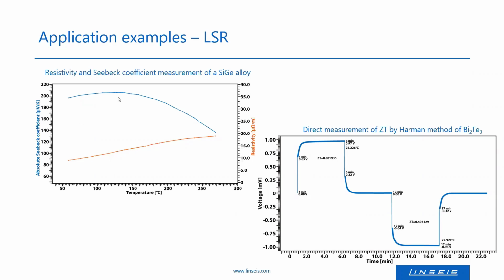Here on the top, one can see a silicon germanium alloy, which is a typically used material in electronics. The silicon germanium alloys are high temperature stable thermoelectric materials and thus are often used under challenging environmental conditions, like, for example, space missions or high temperature waste heat recovery. The LSR here measured a newly developed alloy, and the measurement was performed from room temperature, or about 50 degrees Celsius, to 270 degrees Celsius.